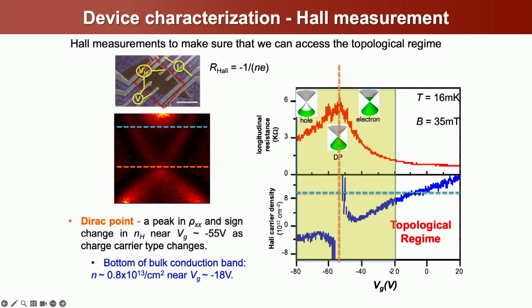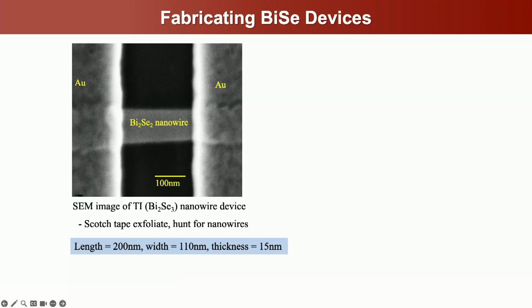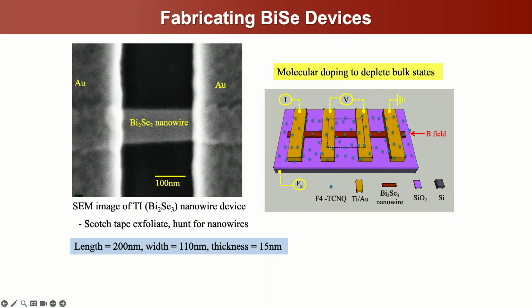Okay, so we fabricate these things. In this case, I'll talk a little bit about some experiments we've done on a nanowire of these. Again, this is just an exfoliated nanowire. We exfoliate, we stick it on the substrate, and we look for wires that look like this. The advantage there is we get really nice edges as opposed to etching it ourselves. So we find wires that look like this. Again, the thickness is about 15 nanometers, right in our sweet spot, and the length and the width are a couple hundred nanometers each. We contact it, put doping on it, and then have the substrate act as a backgate that allows us to tune through the Dirac point.